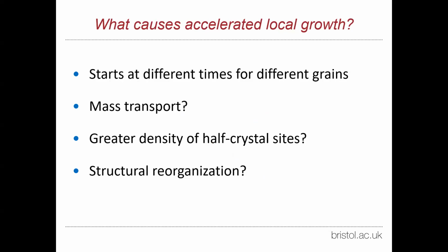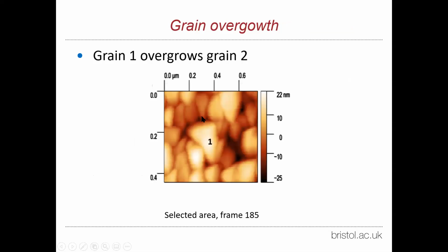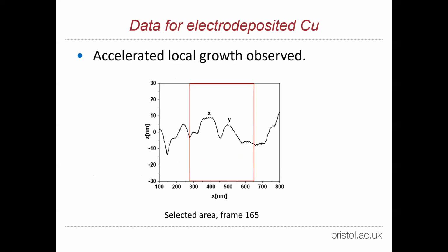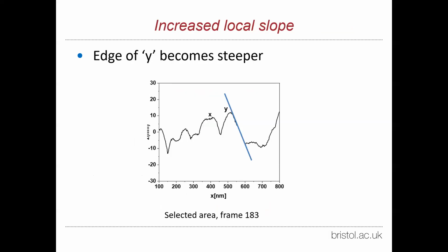So what we've observed with this new technique is that you get this accelerated local growth. You get some grains growing faster than their neighbors. But why would one grain grow faster than another one? It could be mass transport. If you have a supply of reactants to a surface, and that supply is better to something which is higher, then you will have faster growth. But if that were true, the highest grain should grow faster. And if you look back here, Y is initially much less high than X. So that explanation cannot be true.